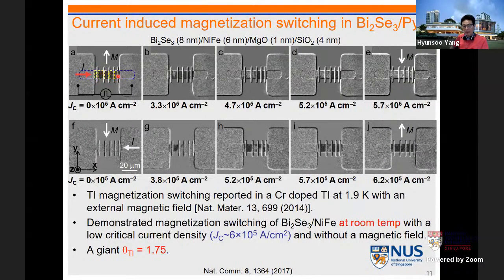So all the black colors indicate the nickel iron pointing in this direction, and we apply charge current from the left electrode, and you can see the white domain propagate. Eventually we can switch into the opposite direction. Now we apply current from the right electrode, then we can switch back to the black domain, indicating this initial configuration. If you look at the switching current density, it's about 6 times 10 to the 5th amperes per square centimeter, about 1 to 2 orders smaller than heavy metal cases, and we can extract an effective spin Hall angle of about 1.75, which matches the previous spin-torque ferromagnetic resonance measurement. So we can now see this exotic, interesting material can even switch a 3D ferromagnet, nickel iron, at room temperature without any magnetic field, in this case because we are using in-plane magnets.